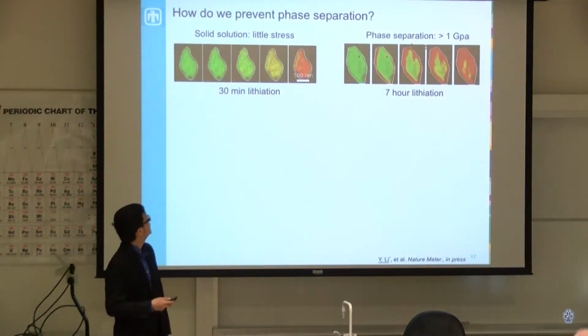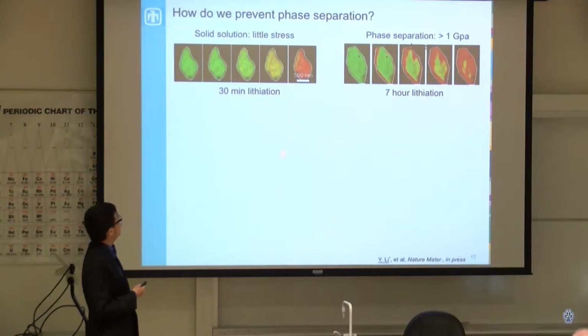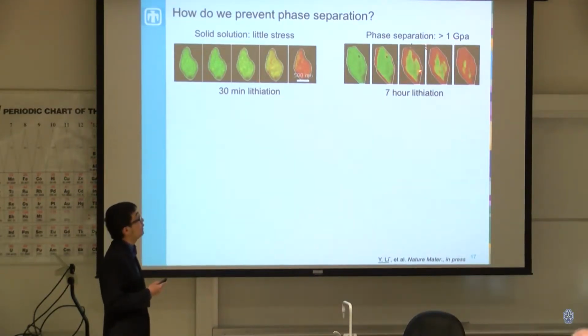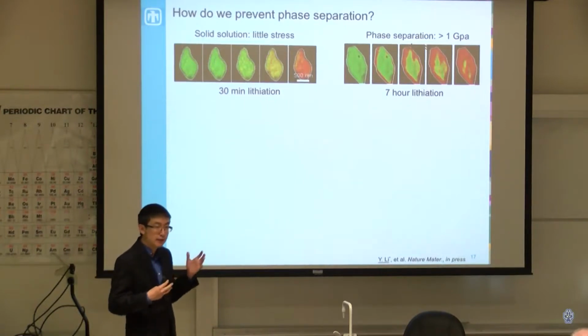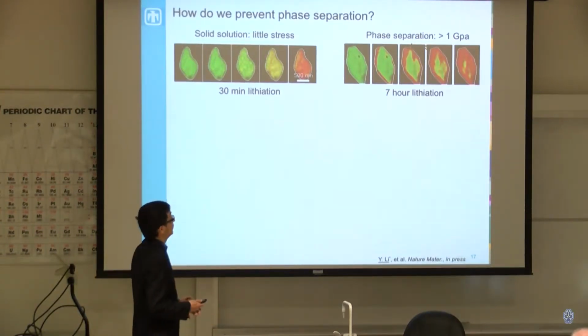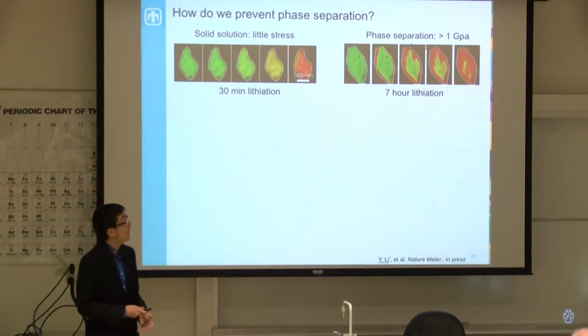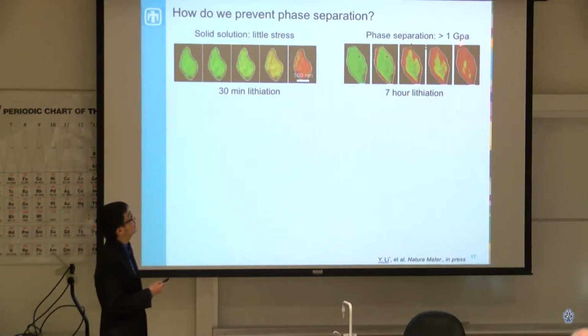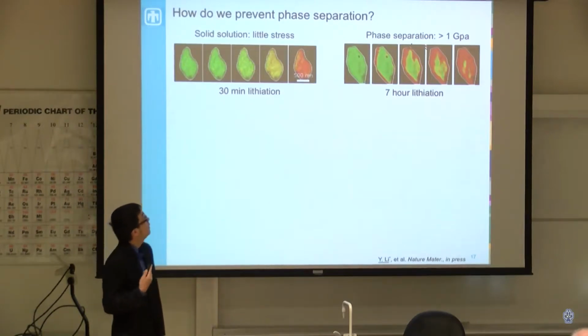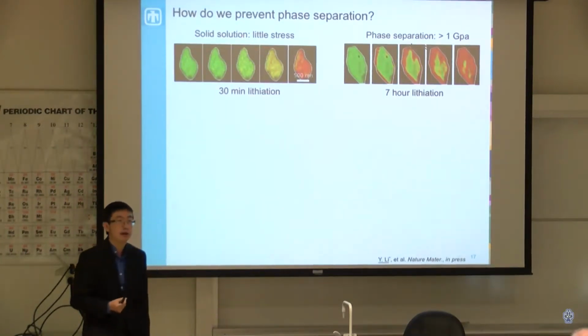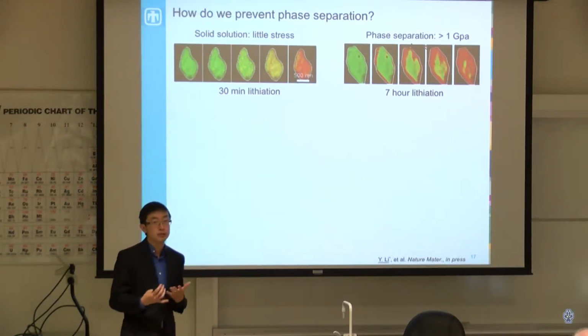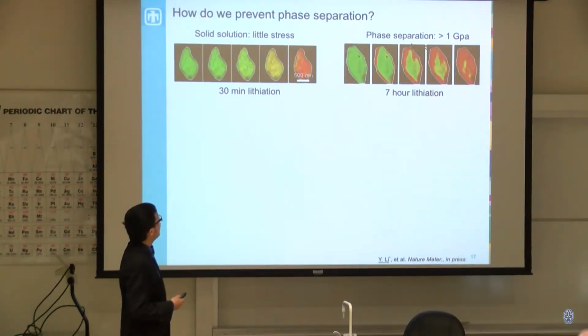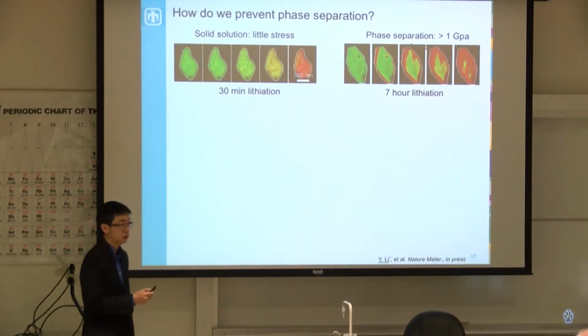So in summary, these results show us that when we lithiate it quickly, we have the solid solution pathway whereby lithium insertion is very uniform within these particles. And then when we charge it very slowly, we get phase separation, so the lithium will like to congregate near other sources of lithium. The difference between these is that this pathway yields about a gigapascal of stress. That P should be a capital P, whereas this one yields very little mechanical stress. We want to reduce the amount of mechanical stress, which can lead to fracture of the material. We want batteries that can undergo this solid solution pathway, where there's a minimal amount of stress in the material.